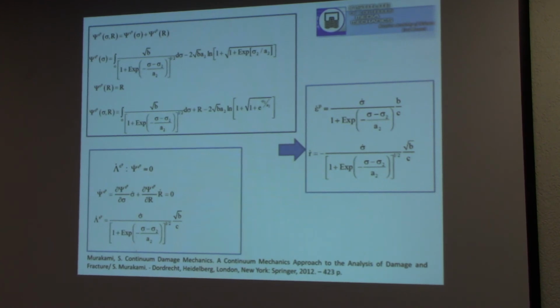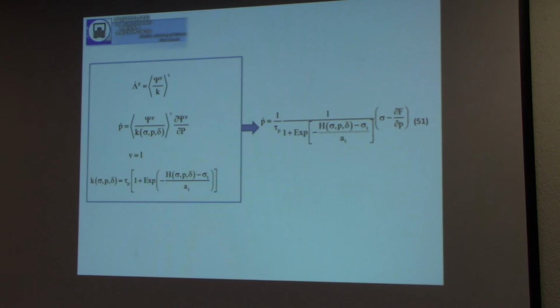Following the standard procedure, we can propose strain sensitive and strain insensitive variables for different kinds of materials. We find the approximation of dissipation potential for plastic deformation, add some ideas about thermodynamics of defects, and here you can see, I'm not going into detail. In the mathematics, it's general. It's a well-known formal approach, and we can obtain the equation for plastic deformation and for isotropic hardening, in the stress insensitive way, and in the stress sensitive way for our structural variables.